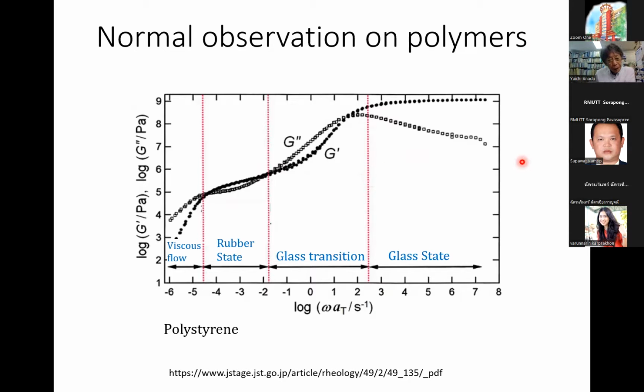But generally, polymers have several peaks of imaginary part. This is polystyrene, one of the typical polymers. This peak shows glass transition. In this region, material changes gradually from soft state to hard state. On the high frequency side, hard state, glassy state. On the low frequency side of the glass transition range, the rubber-like state. And in a still lower region, viscous flow occurs.